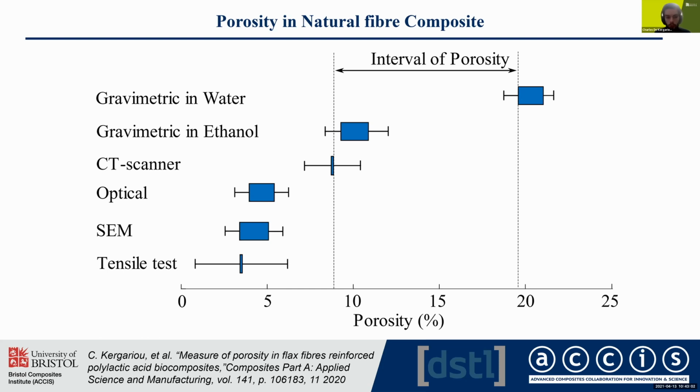And when we went through all the different techniques, we quickly realized that it would be difficult for us to obtain a precise value of the porosity and be sure that we were measuring every single pore in it. So basically, instead, we were able to define an interval of porosity in which we were sure our porosity was located. You can see it in this graph. It was defined by the gravimetric measurement in water as upper bound and the largest optical measurement as lower bound, in our case the CT scanner, and we were able to obtain an estimation of the porosity thanks to gravimetric measurement